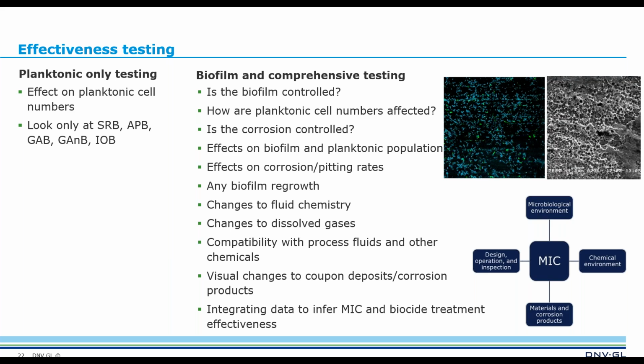So this more comprehensive testing would look at whether a biofilm is controlled, in addition to a reduction in planktonic numbers, and what the effects of the biocide are on the biofilm and planktonic community composition and activity. So not just looking at how the numbers have changed, the abundance, but also looking at if there are any changes to the composition and if there are changes to the activity. And more importantly, because biocides are applied to mitigate MIC, it is important to investigate if general corrosion rates and pitting corrosion rates are reduced.